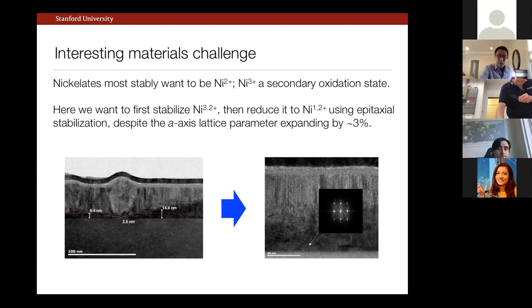and we want to use epitaxial stabilization in thin film form, as discovered by Professor Shimakawa's group. And all the while, the in-plane lattice parameters are changing by about 3%. Okay, so it's kind of a mess, but quite an interesting challenge, actually. And so let me give you a picture of the kind of sample we're probably looking at in this partial transition.